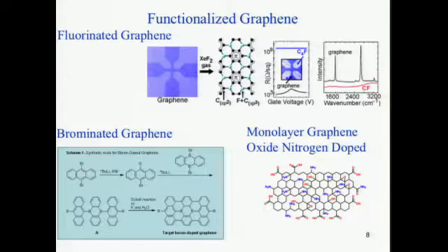And so there's many schemes out there for how to functionalize graphene. Here I'm showing a fluorinated graphene where, using some gas, the graphene lattice was fluorinated, and you have some varying degrees of the pi system and sp2 versus sp3 bonding. And you can see here in the Raman spectra, which is indicative of the pi systems in graphene, that after you fluorinate it, you no longer have the signature of a graphene